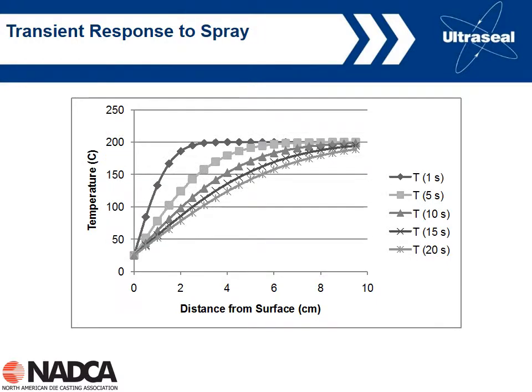And we also have a similar slow response in terms of getting heat out of the die. So this is the inverse of what we just talked about. Now we've got the die at room temperature. We're basically spraying room temperature water onto the die. Again, we're looking at temperature change versus distance from the surface. And again, the die is very slow to respond in terms of actually cooling the interior of the die. And so this is why we have limited effect in terms of what we're doing with spraying.